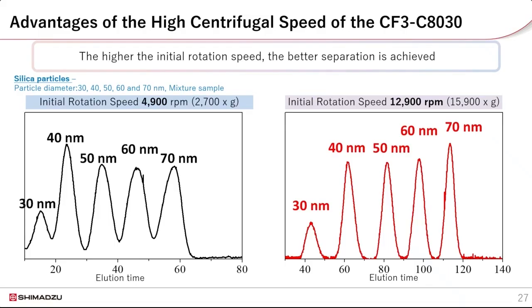On the left side, we can clearly see the suboptimal resolution between the sizes and the smallest size almost coming out in the void volume. The higher speed results on the right-hand side show baseline separation as well as the smallest size eluting away from the void. This demonstrates that the higher centrifugal speeds of the Shimadzu system are necessary to achieve higher resolution and higher sensitivity when separating and analyzing nanoparticles.